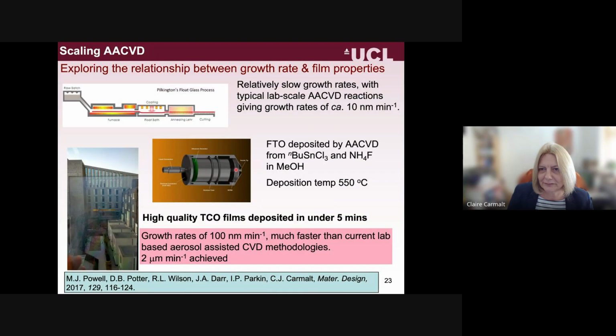Okay, just the last thing I wanted to mention to you was about this whole issue with scaling AACVD. Just as a last slide for you. So essentially what I mentioned before is that the AACVD reaction can take between 20 and 60 minutes. However, when I mentioned the industrial process, when you're growing your coating within the float bath, that could be, I don't know, a TiO2 coating for self-cleaning applications. That deposition is typically done in less than 60 seconds because the glass is continuously moving. So obviously at the moment the AACVD isn't compatible with that because you can't really stop it for 20 to 60 minutes to do the coating.